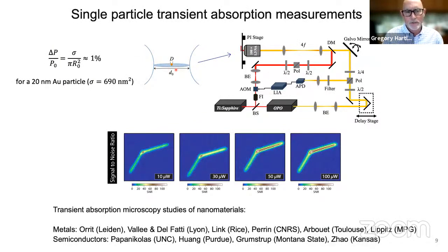And so this is a cartoon, again, lots of cartoons. It's a picture of the size of a diffraction limited laser beam of green light at a sample compared to a 20 nanometer diameter metal particle, right? Can you see that the laser beam is going to be much, much larger than the particle? So luckily for us and for many applications, metal particles absorb very strongly. So they absorb more than just their geometrical cross section. So a 20 nanometer particle with green light, in a diffraction limited experiment, will absorb about 1% of the light. Okay, not much, but actually, it's measurable.